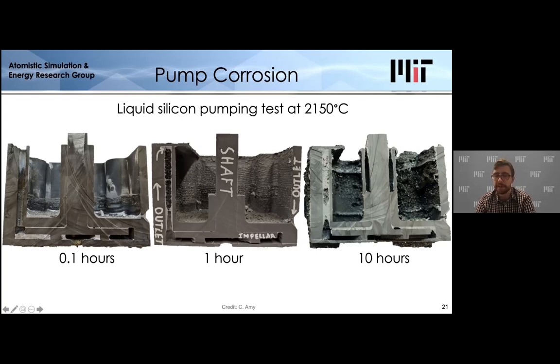And what's happening is actually the bottom edge of this impeller is corroding. Basically, it's forming silicon carbide, and that silicon carbide is being torn off through frictional contact and then forming a new layer of silicon carbide. So this basically eliminates that protective skin that we observed in previous experiments and becomes a serious problem.